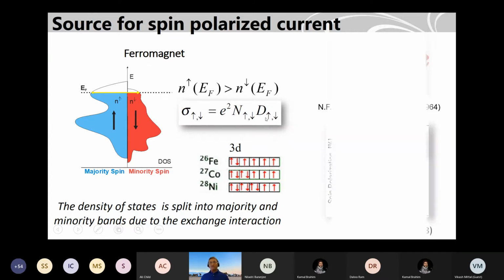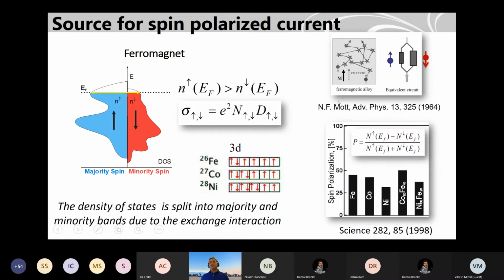And this comes directly from the Mott formula that Mott proposed, that there will be two parallel channels in a ferromagnet, one for upspin, other for downspin, and they have different resistances in this material. And after several years, people found out that that is true. And these ferromagnetic materials, when the current comes out of them, are spin polarized. So in 1998, this paper shows what the spin polarization of iron, cobalt, nickel, and their alloys, and any other ferromagnet is. It's around, let's say, 40 to 50%.